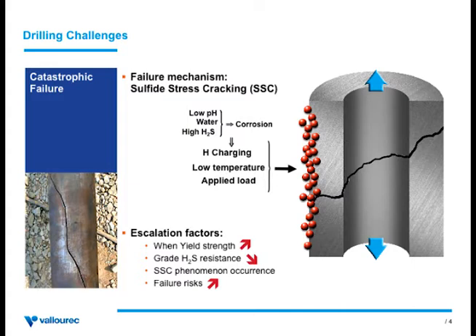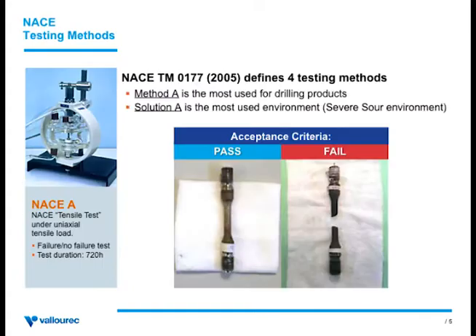There are several escalation factors. Not all the grades will be susceptible the same way. The higher the yield strength of the material, the higher the risk of having a failure. The material is more brittle if the minimum yield strength is higher. So the way the industry qualifies sour service drill pipe, to be used in a sour well or potentially in a well where they could be exposed to H2S, is we use one of the NACE standard methods, which is the NACE TM0177, which was put together in 2005.